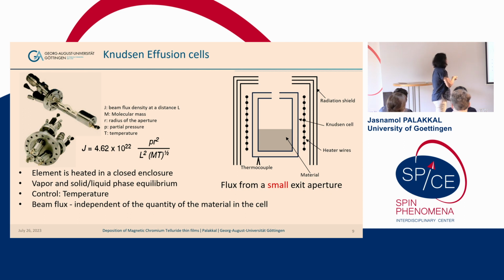It is just like a thermal evaporation, but you need to have a closed cell. You keep the material inside this closed cell and you heat the cell by using heater wires, and the material will be either sublimated or evaporated, but inside the cell, and after some time there will be a vapor and solid or liquid phase equilibrium achieved. In that case, the partial pressure inside the cell will be constant, and you can control the flux rate of the material coming out of this exit aperture by varying the temperature of this cell. So this is how a Knudsen cell works, and if you want to evaporate highly volatile material, you have to use such a device, otherwise you will destroy the entire chamber.